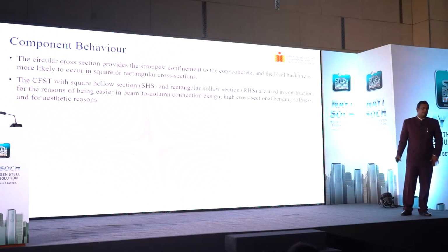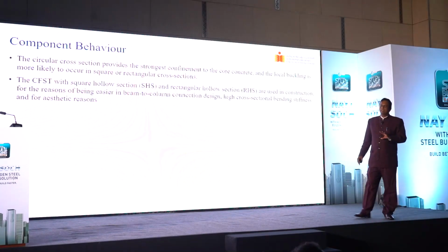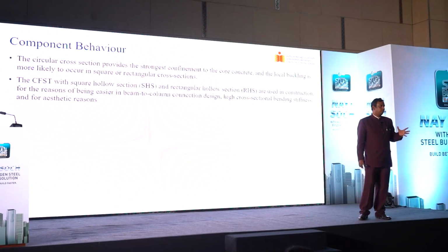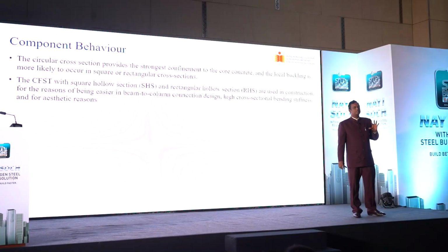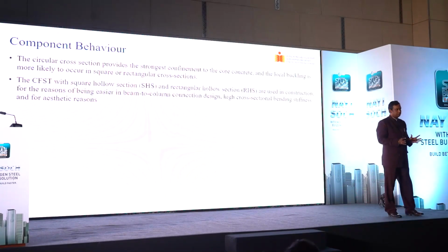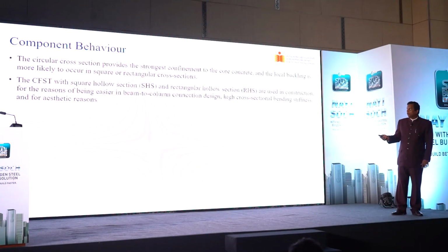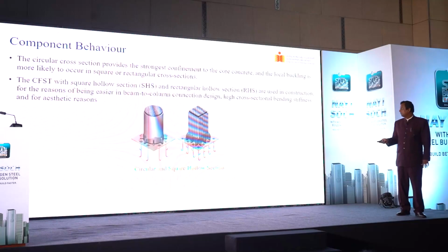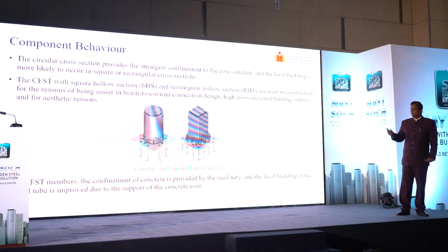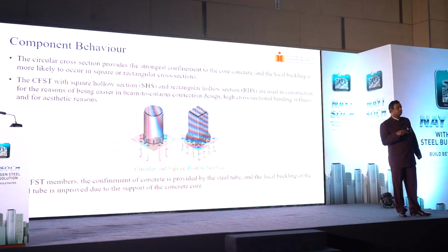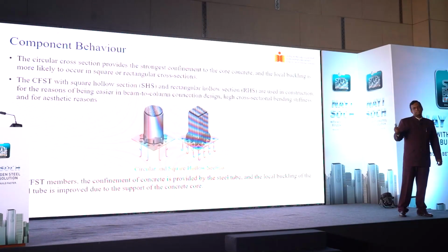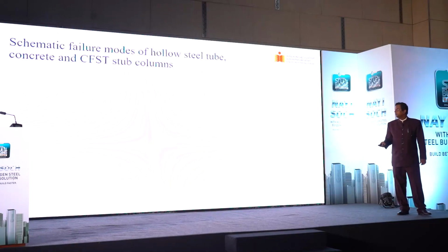On component behavior, the most useful component is a tubular structure from a strength point of view, but there are some challenges associated with connections when you use a circular tubular section. From a strength point of view, circular tubular sections are very good. When we talk about connections as well as other aesthetics, the square sections are preferred. But the confinement provided by the steel tube is much higher, so the load carrying capacity, simply because of the geometry, is much higher in a circular tubular section.